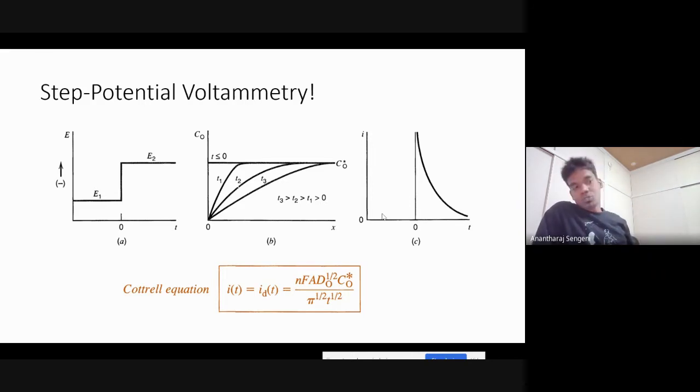So in essence, we are exposing much more area than what we actually wanted to expose, so you will see such an increase in current density after a certain time of performing chronoamperometry. So these are the instances where we see a change in current density in the case of charge transfer controlled reactions.